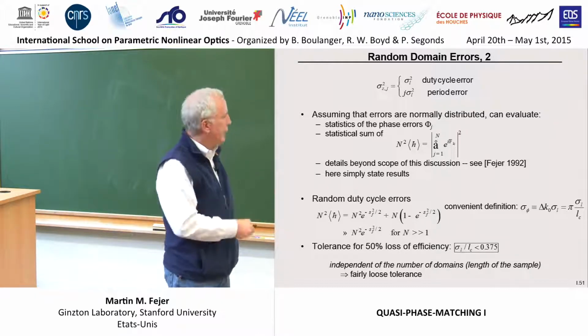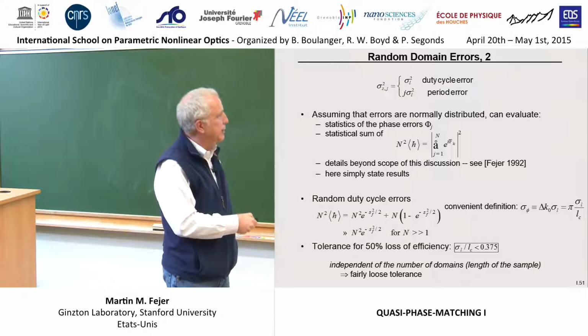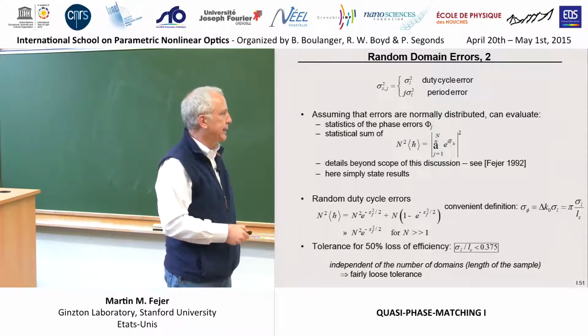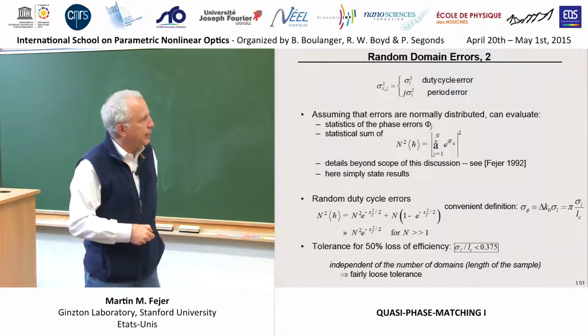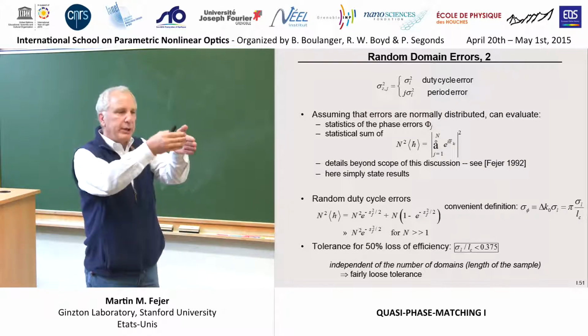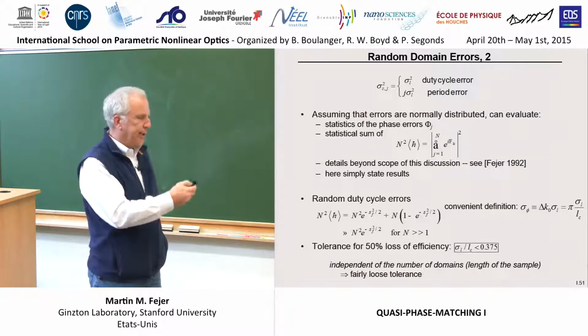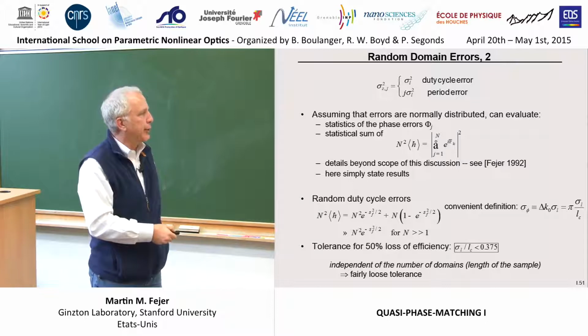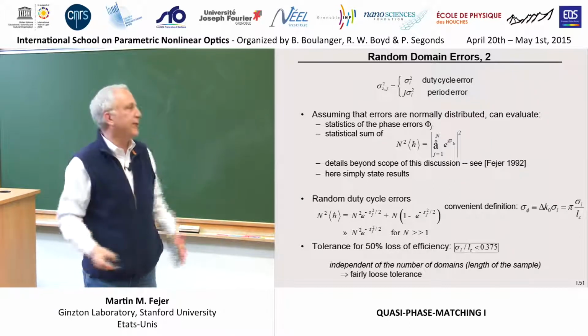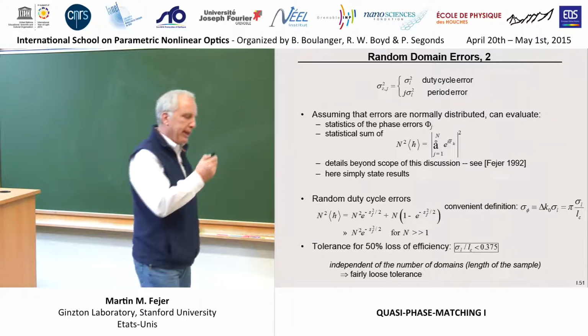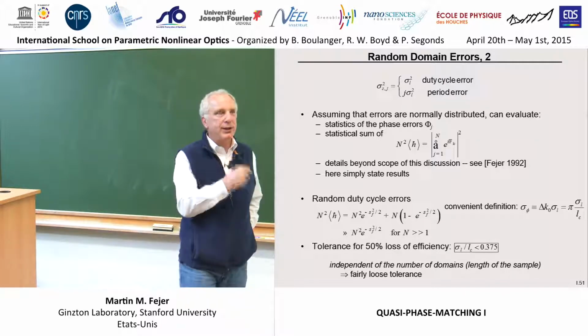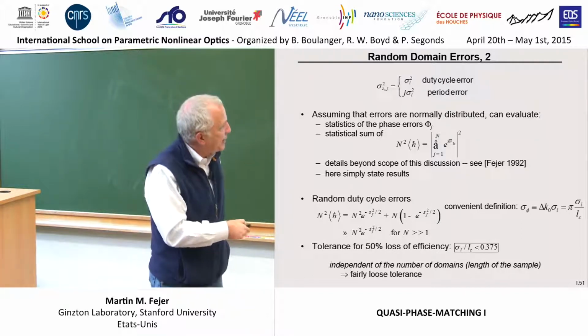If you work out what would reduce this thing to 1/2 of its nominal efficiency, you can have domain width errors, statistically speaking, that are about 1/3 of a coherence length and still retain 50% of the efficiency. An important thing that we didn't realize the importance of is this piece here.